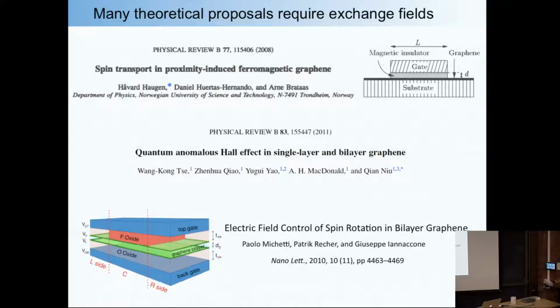They say, what if you had spin transport and you had proximity-induced ferromagnetic graphene? So you can make graphene act like a ferromagnet. All you got to do is put next to it a magnetic insulator, like here. Or you could get this quantum anomalous Hall effect in single-layer and bilayer graphene. Just do it. Or if you had a bilayer, you could actually use electric field to control the spin rotation.